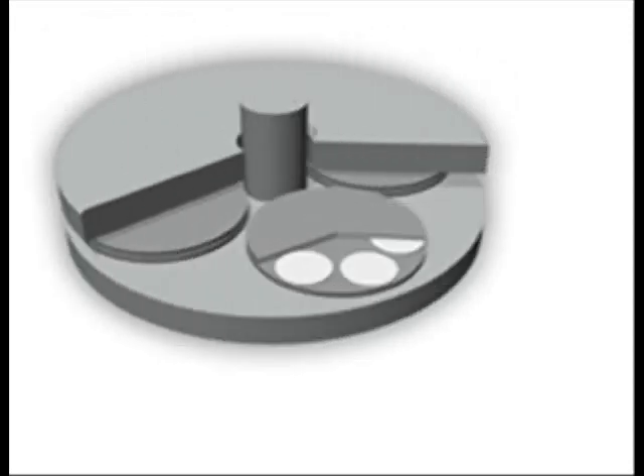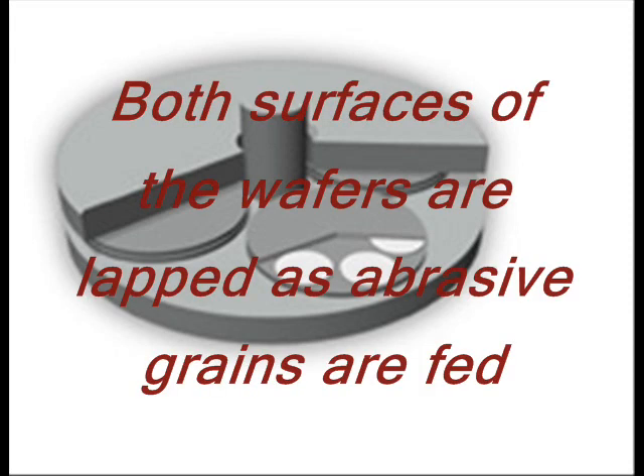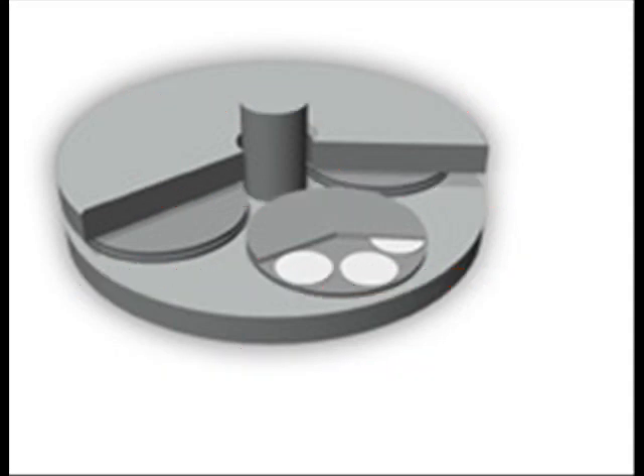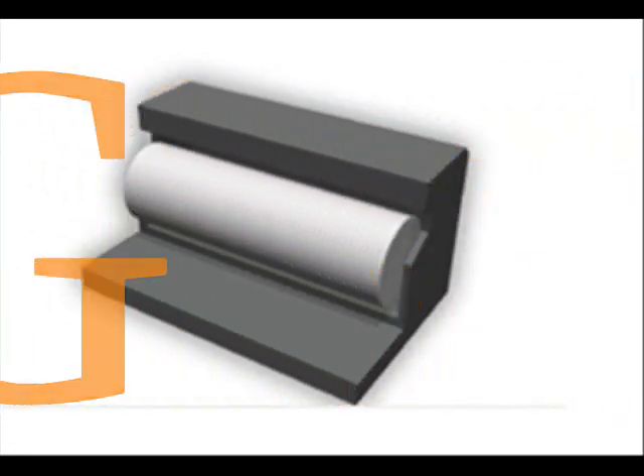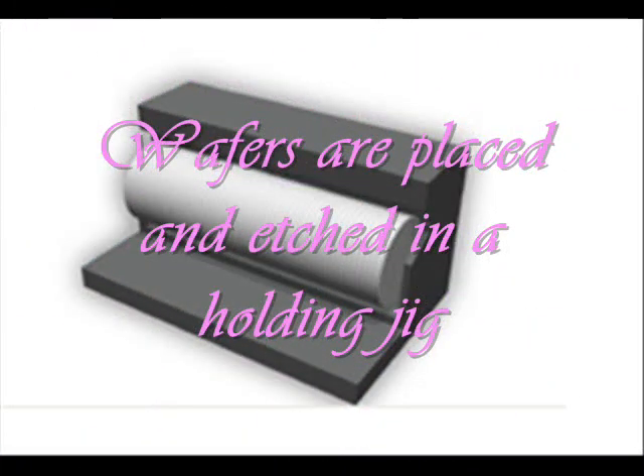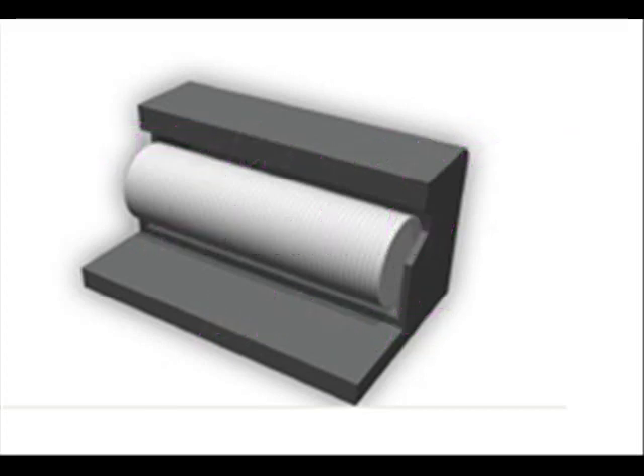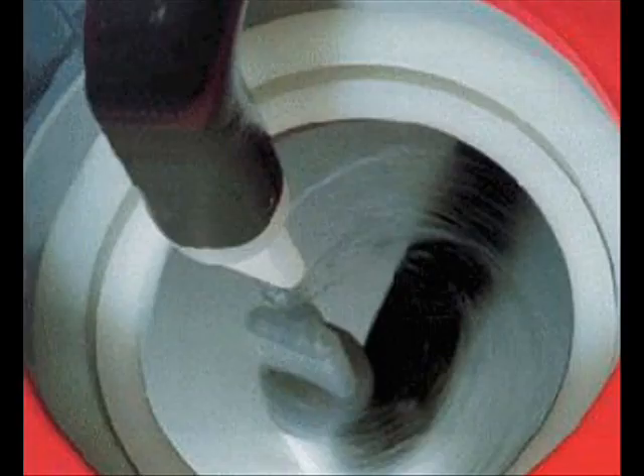Lapping. Double-side lapping. Wafers are set in a carrier which spins between two rotating lapping plates. Both surfaces of the wafers are lapped as abrasive grains are fed. Etching. Double-side chemical polishing. Wafers are placed and etched in a holding jig that rotates in an acid-containing etching solution to completely remove the damaged surface resulting from the previous lapping.